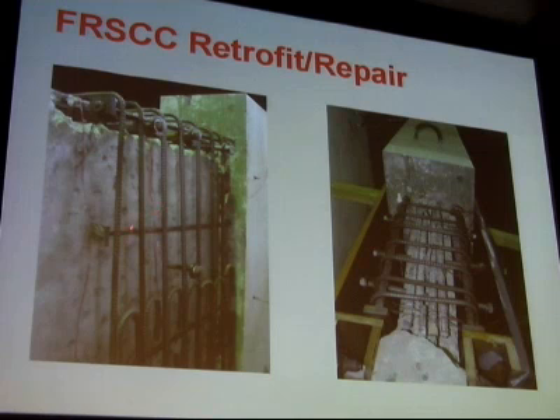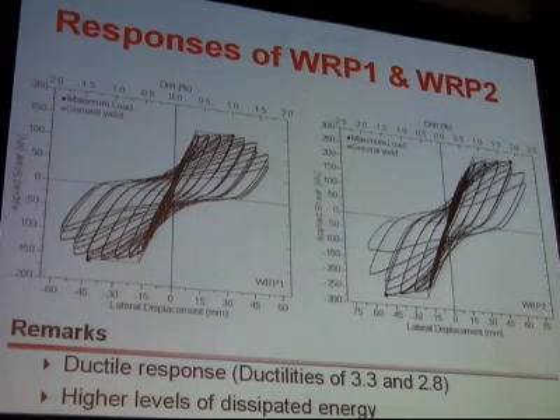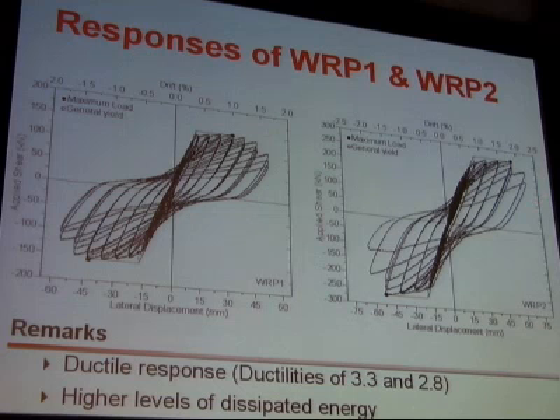You can see that we used headed bars going into the foundation wall to get really good anchorage of this longitudinal reinforcement. This surface was roughened, headed bars again, and here are the through bolts going through the wall to give adequate shear connection. You can see the top view over here. So that is now a capacity-protected region, and when we do that retrofit, we see significantly improved responses, and this could be used for certain cases if you're looking at retrofit.